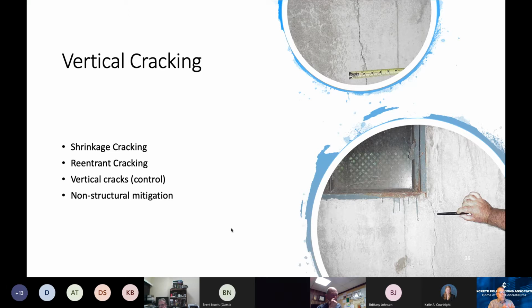Back to my vertical cracking, these are your shrinkage cracks. I showed them before. So you've got a vertical crack here. This one's an interesting vertical crack because to the right, you can see a tape measure there, and the crack is on the 2-inch mark. The form joint is on the 6-inch mark. And so this vertical crack is slowly moving closer to that form joint. So in this particular case, there was a weakened plane, probably based on the percentage of aggregate that was in that wall thickness, that allowed the crack to go up 6 to 8 inches away from the form joint that should have been